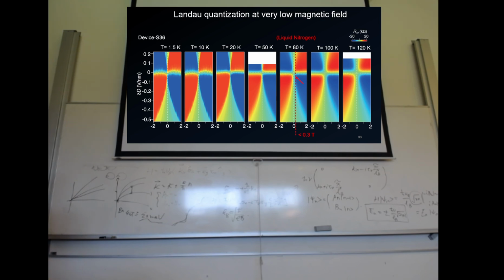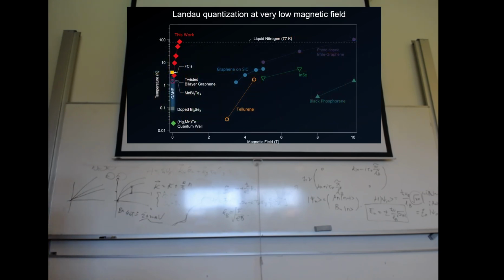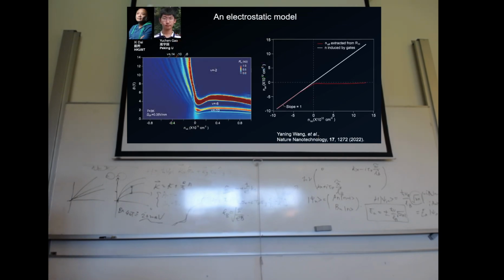So that means somehow by just changing the substrate of hBN into some kind of new material, we got a larger Fermi velocity and larger Landau level spacing and a more robust quantum Hall effect. So this is the experimental data as compared to all the existing systems that are still graphene but just modified. This is one way to sacrifice a little bit of magnetic field, but significantly enhance the temperature to observe this experimental phenomenon.